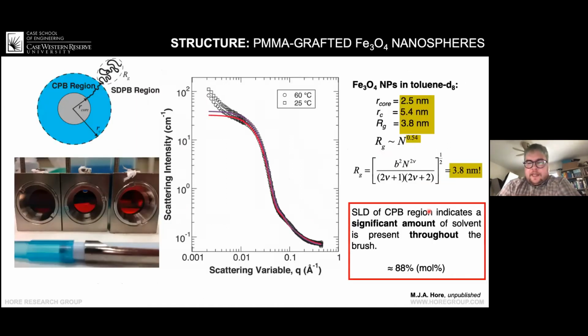Now, this is just a brief slide. I never published this. I will never publish this probably, but this was the iron oxide particles that we measured originally. And the work I showed you was in a polymer film. This is in solution in deuterated toluene. But by fitting these curves with the same model that I showed you before, we can get an idea of how much solvent is in the brush. And just a rough back of the envelope calculation shows that of the moles of everything that's in the brush, including the polymer, the solvent makes up about 88% of the atoms in the brush region.